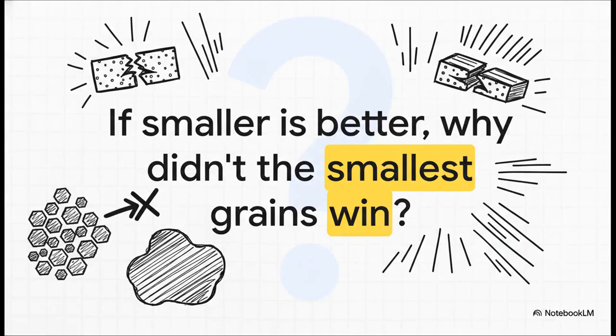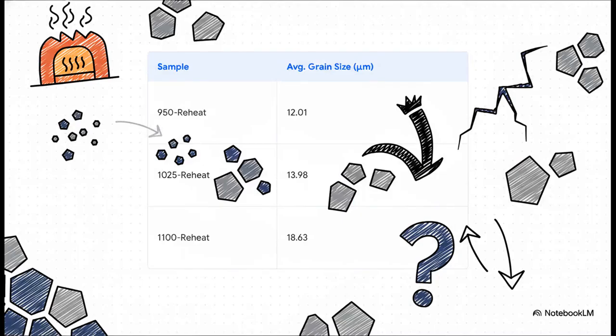And this is where the story gets really interesting. Because if the rule of thumb is smaller grains are better, then you'd totally expect the sample with the absolute smallest grains to have won the toughness test, right? Well, that's not what happened. When the researchers actually measured the grain sizes, they found a bit of a surprise. The 950-degree sample, the one that came in second place for toughness, it actually had the finest grains. Our champion, the 1025-degree sample, had slightly larger grains.